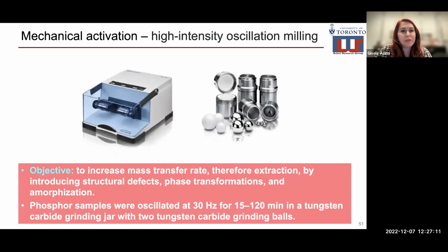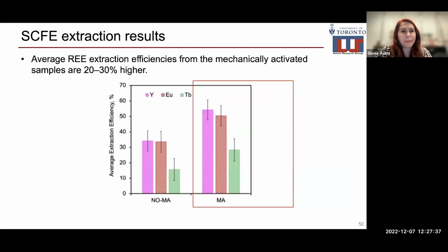To enable this, we used mechanical activation by high-intensity oscillation milling. The objective was to increase mass transfer rate, and therefore extraction, by introducing structural defects, phase transformation, and amorphization. Phosphor samples were oscillated at 30 Hz for 15 to 120 minutes in a tungsten carbide jar with 2 tungsten carbide grinding balls. After mechanical activation, we performed SCFE, and we saw that the extraction efficiencies are improved by 20 to 30%.